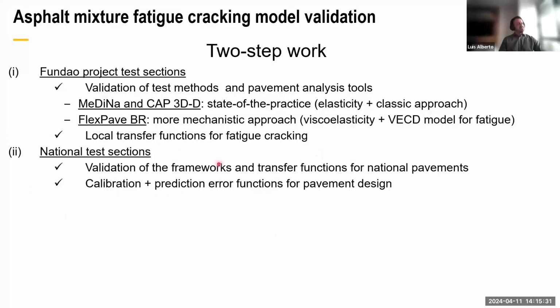So here is the two-step work for asphalt mixture fatigue cracking model validation. In the first step, we analyze the Fundão project test sections, so we have a kind of local transfer function for fatigue cracking. We use different programs, but here I'll be focused on the FlexPave one. And in the second step, after we validate the models by the local transfer solution, we expand the calibration to our national test sections. So we could validate it and calibrate and have some prediction error functions.